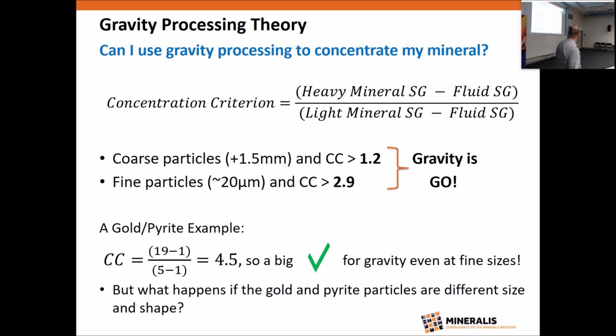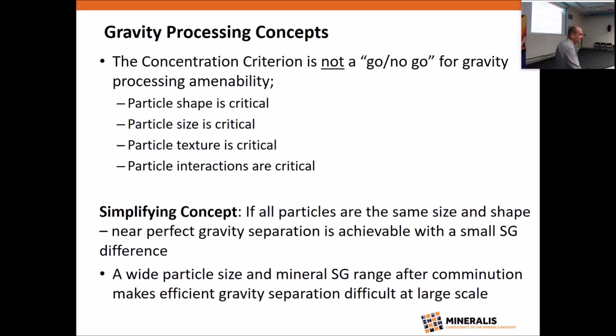So what it says is for coarse particles a concentration criterion over 1.2, and for fine particles over roughly 3, say gravity's a goer. And I've used a pure mineral example for gold and pyrite here, which indicates you're going to have absolutely no problems separating gold from a pyrite host. But, and there's always a but, what happens if the gold and pyrite particles are a different size and shape?